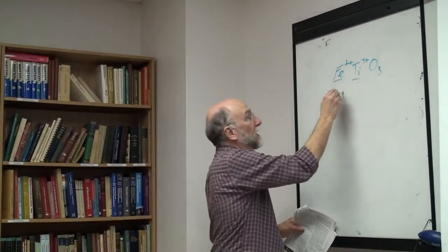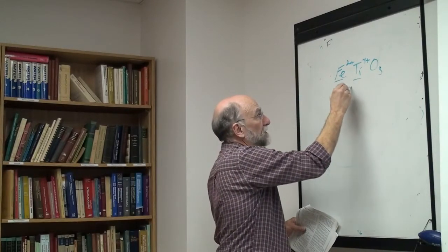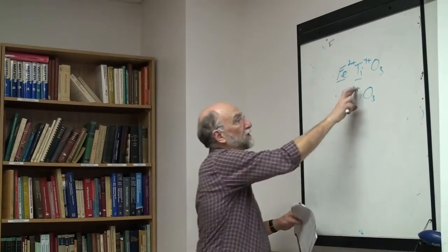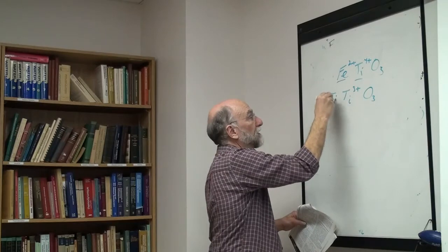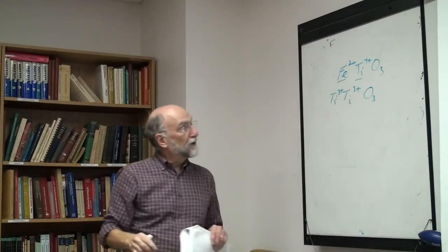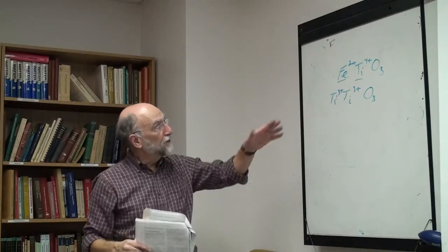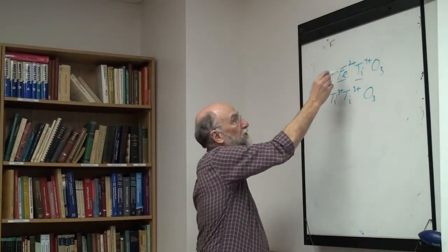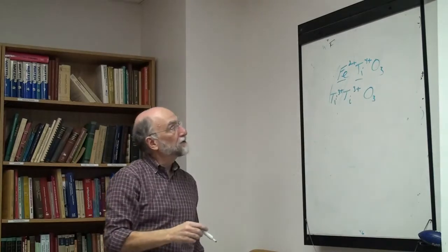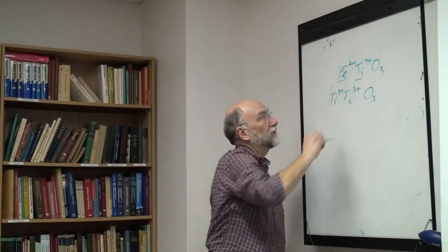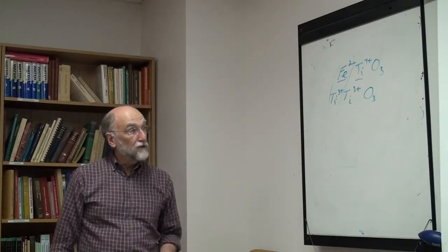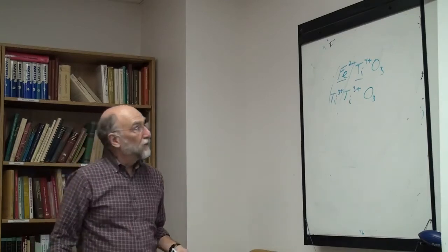Ti2O3 is Ti3+, Ti3+, O3, where the 2 titaniums can be considered to be on 2 separate sublattices. So when you make a solution of the two, the iron and the Ti3+ can mix on one site, and Ti4+ and Ti3+ can mix on the other site. The oxygens stay constant, so there's a third oxygen sublattice, but we don't have to worry about it.